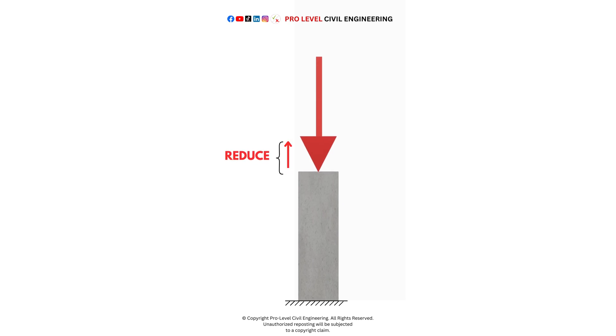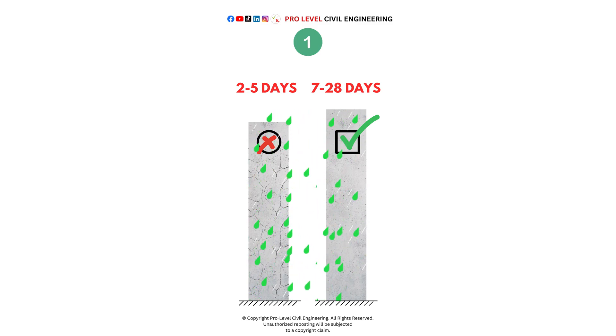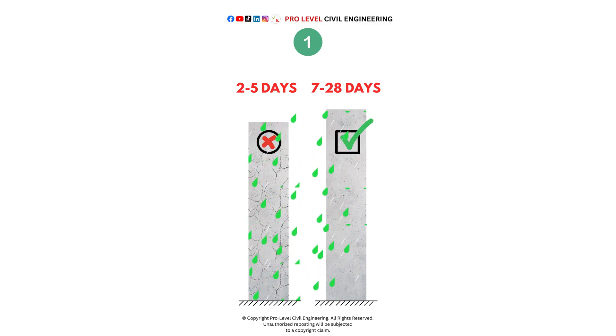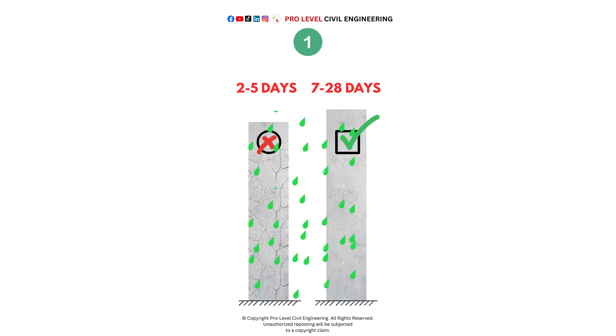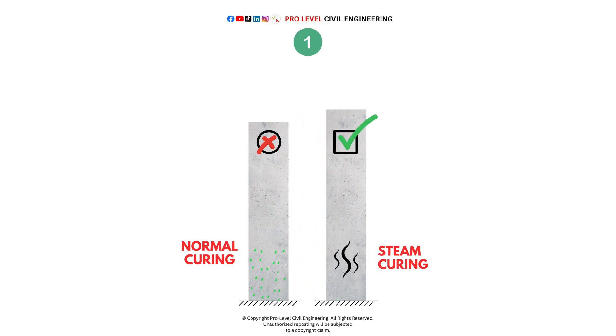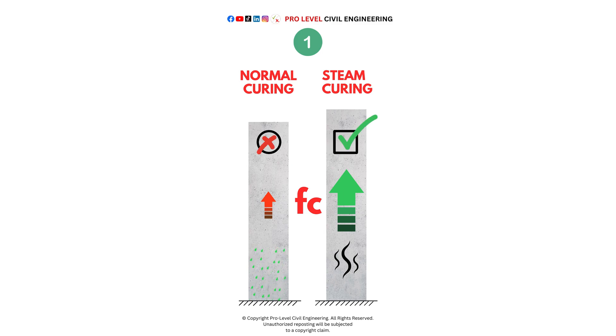The effect of creep can be reduced by: 1. Longer concrete curing — the longer concrete is allowed to cure before any loads are applied, the more fully it strengthens, resulting in less creep when loads are eventually applied. Steam curing will also reduce creep, because it causes the concrete to gain strength more quickly. As a result, concrete subjected to steam curing will experience less creep compared to concrete cured more slowly under normal conditions.